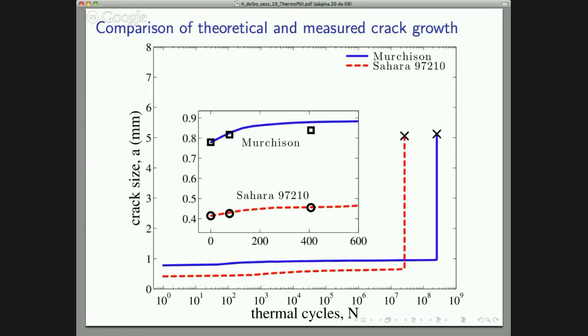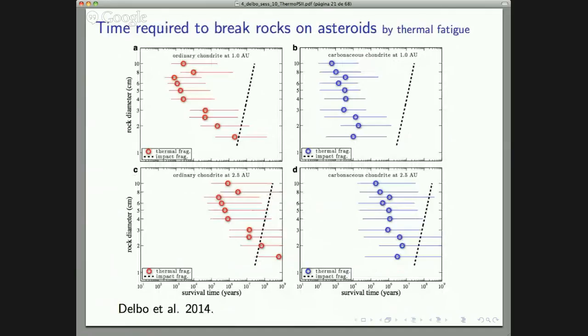Then we used this model to extend the number of cycles to the lifetime of asteroids, and we compared the time it takes for a crack to grow through a rock of this diameter as a function of time. The red on the left is ordinary chondrite, the blue is carbonaceous chondrite, top is at 1 AU, bottom is in the main belt. The straight line is the Hörz et al. time to break objects by micrometeorites. And you can see we are not always, but we are kind of faster than the micrometeorite bombardment. Some new experiments.